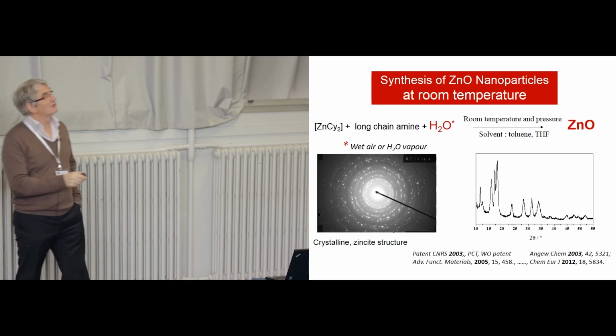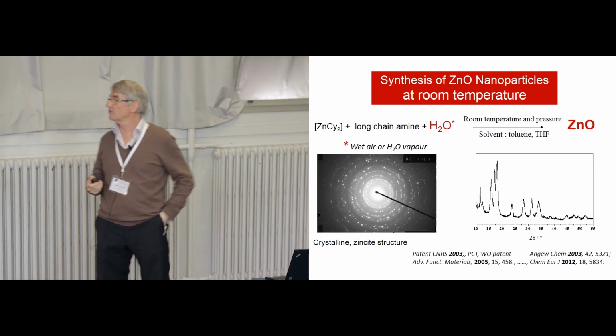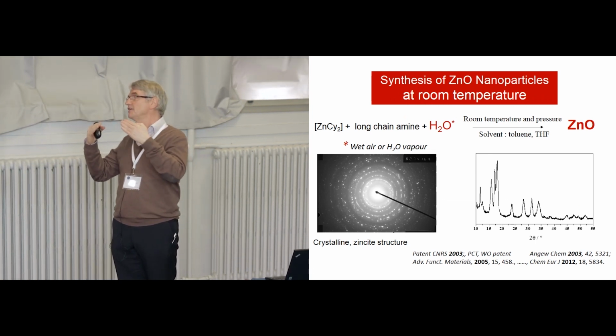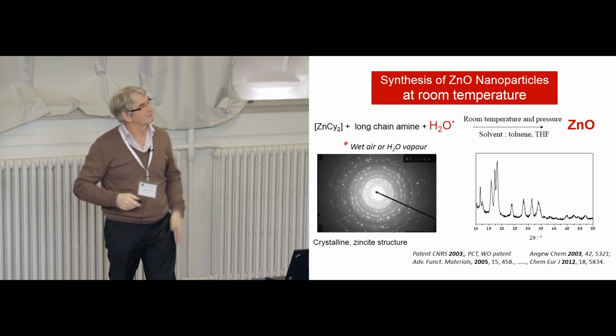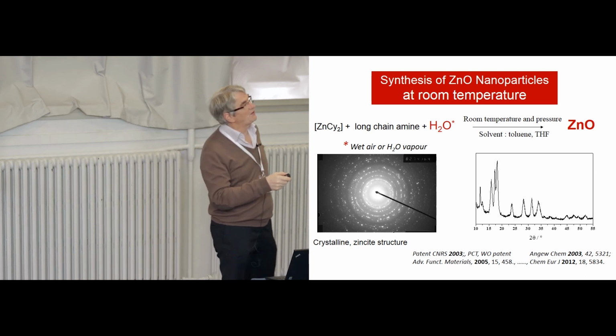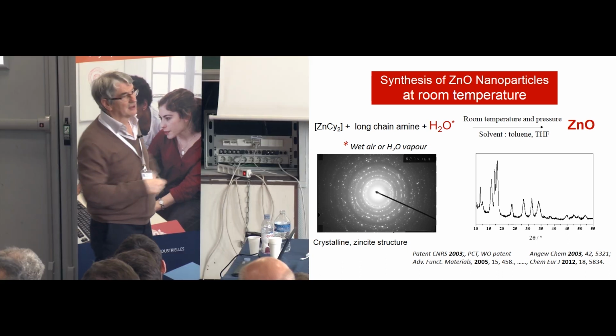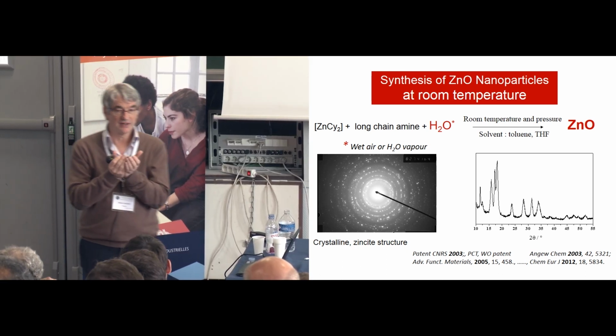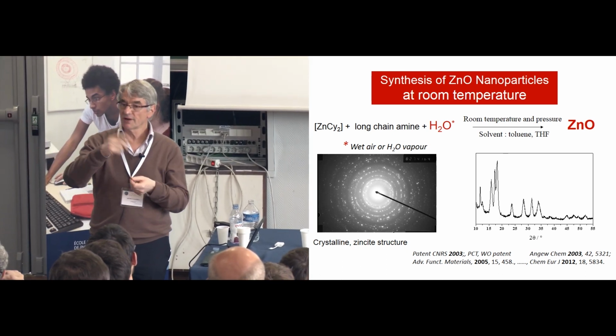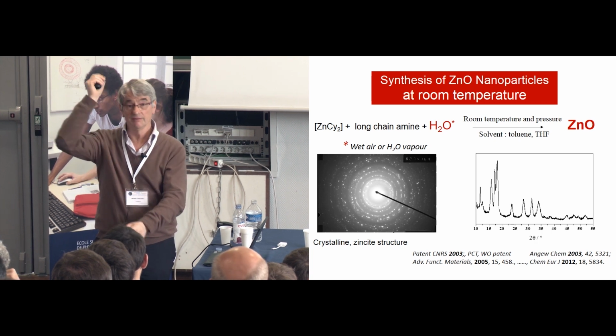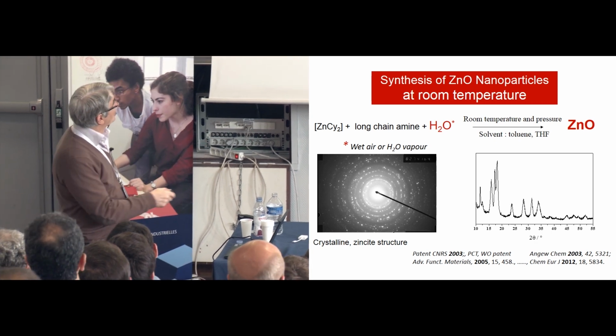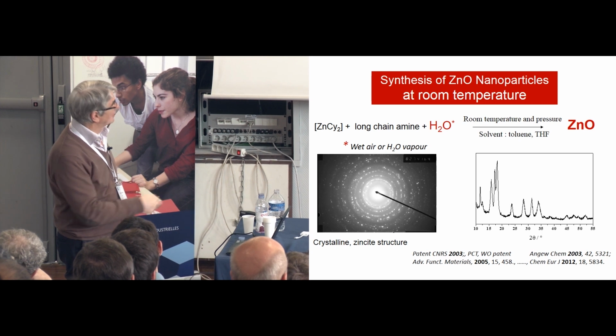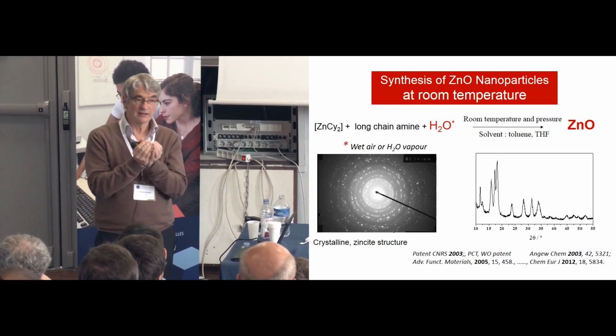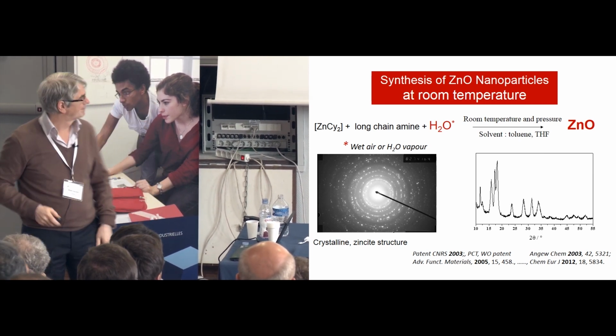So this is a high-energy precursor. The cyclohexyl is a little bit less reactive, but still. And then we feed it in solution with water from the gas phase, either water brought by an argon stream, or even we can open the flask. And then we can make like that zinc oxide, which is crystalline.